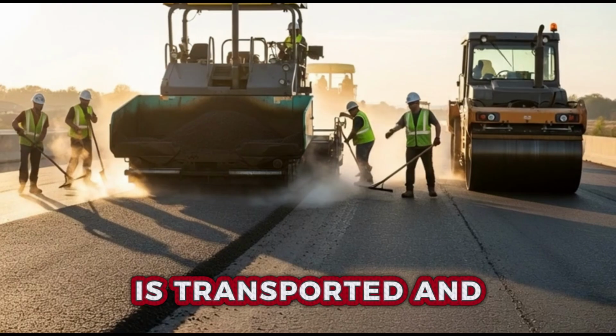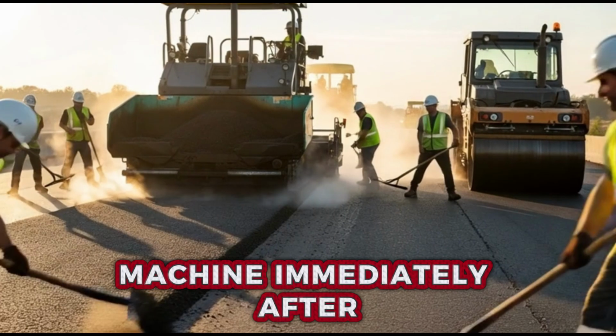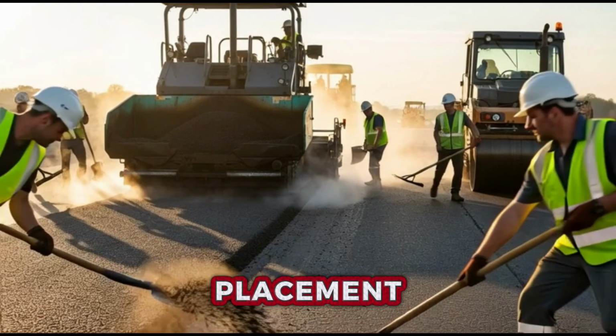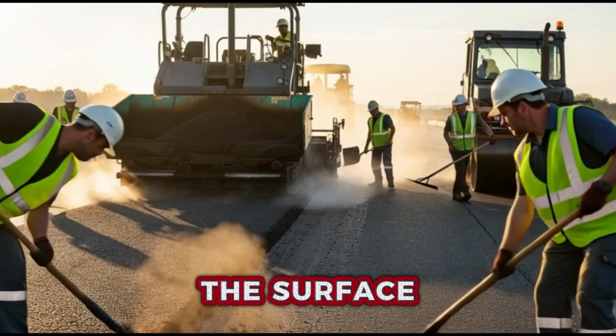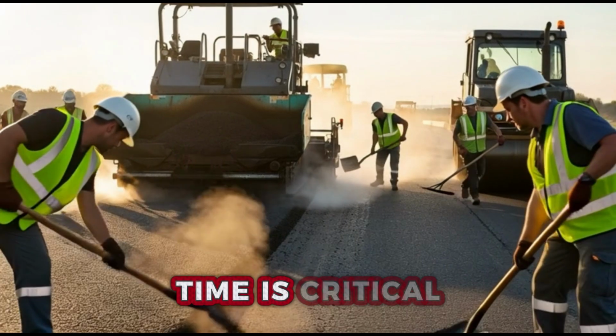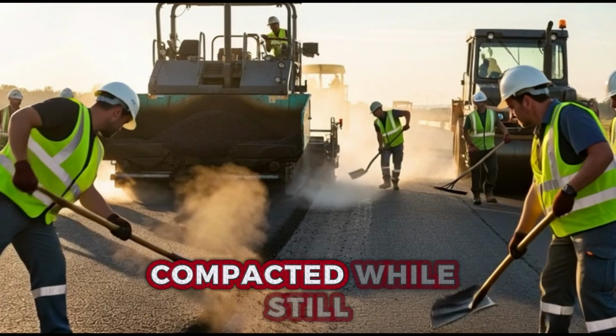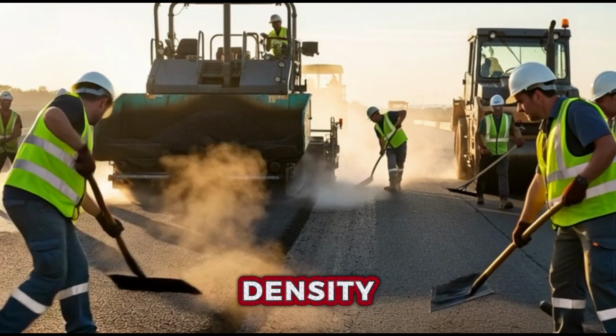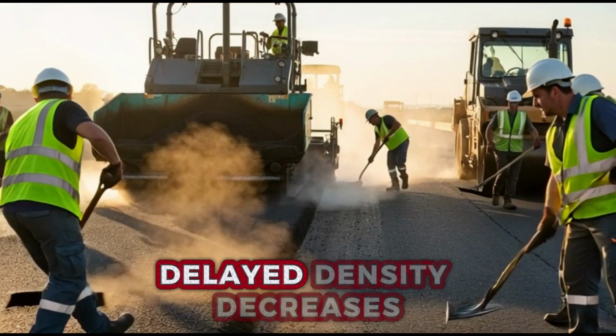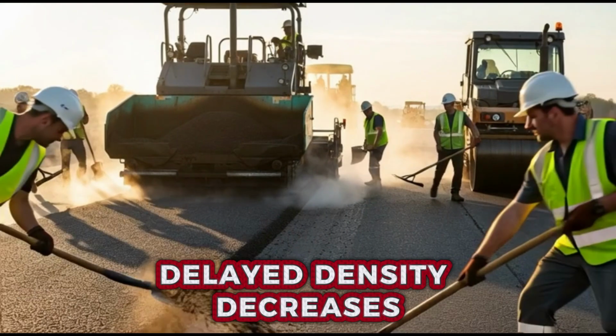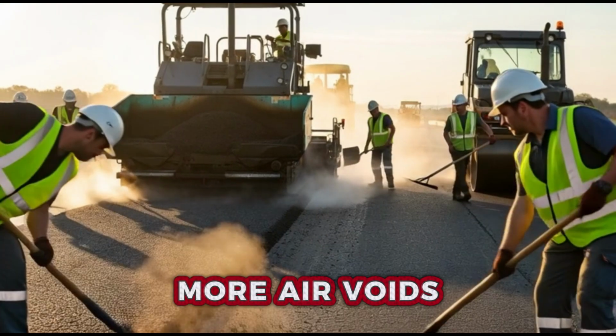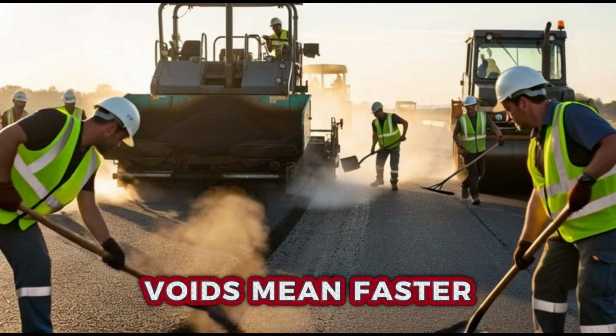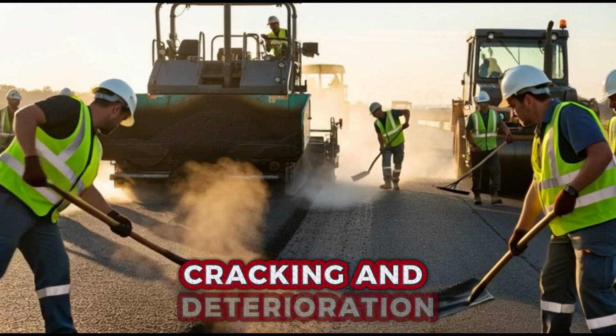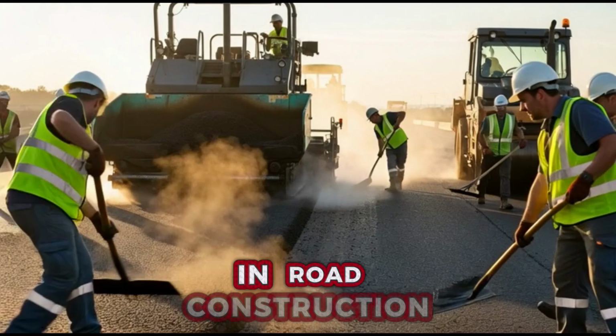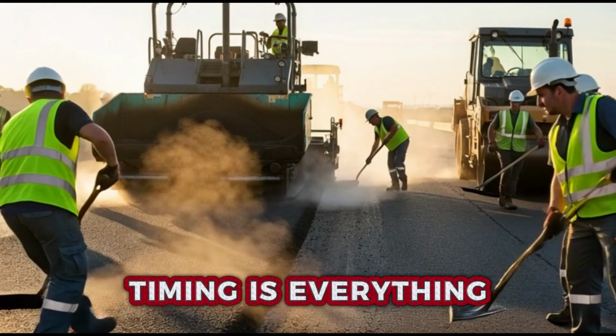The hot mix is transported and laid using a paver machine. Immediately after placement, vibratory rollers compact the surface. This window of time is critical. Asphalt must be compacted while still hot to achieve proper density. If compaction is delayed, density decreases. Lower density means more air voids, and more air voids mean faster oxidation, cracking, and deterioration. In road construction, timing is everything.